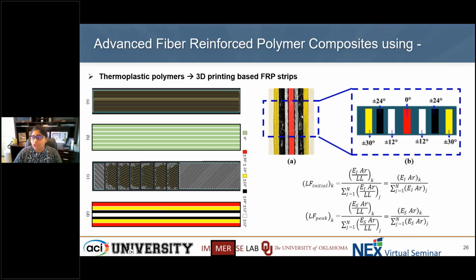So if you look at this particular strip, an FRP strip, it would consist of different orientations. For example, the red is related to 0 degrees. The white strips are related to a 12-degree oriented fiber. The black strips are related to a 24-degree, and yellow in this particular design is related to 30 degrees. So compared to 0, which is the traditional way of building an FRP composite, we have other directions with respect to 0 at 12, 24, and 30 degrees orientations. So these were 3D printed, and the mechanical properties, especially in terms of tensile strength and ductility, were understood.